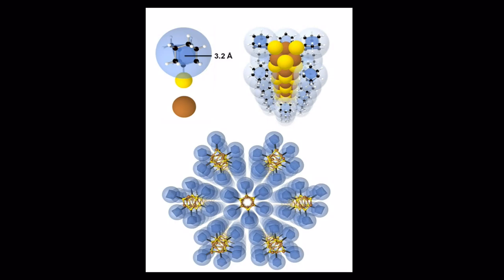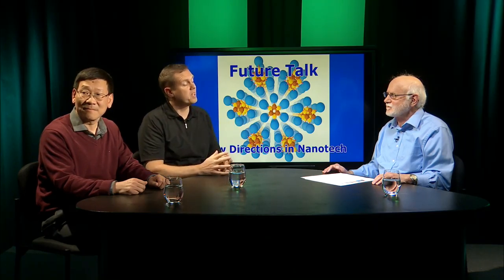On the right-hand side, you can see those diamondoids arrayed around this inner core. That nanowire is actually the smallest nanowire you could make — a three-atom cross-section, composed of three sulfur atoms, then three copper atoms, three sulfur, three copper in an alternating array. That's the inner core. If you take one more atom out, it's now a ribbon instead of a solid core. So this is really the smallest nanowire you can possibly make. It can conduct electricity, and the diamondoids are an insulating layer around it that keeps the electricity inside the wire — just like the insulation on wires in your house.